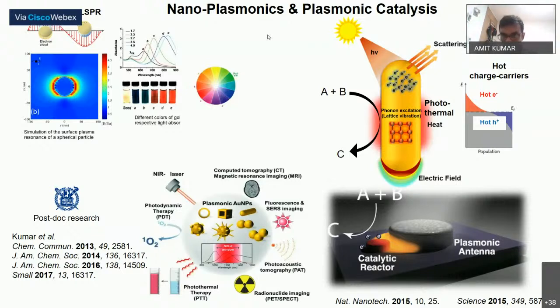And when these phonons relax, they generate highly localized heat. So the combined effect of the photothermal effect and generation of charge carriers can promote chemical reactions. Imagine the scenario: we combine the high catalytic activity of the nanoparticles with these reaction-promoting physical effects. We can create a very interesting combination of designer catalyst which can be operated by light.